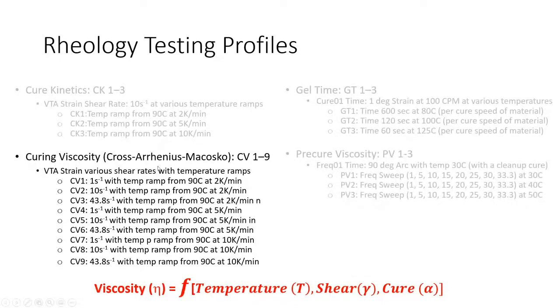Thank you. In curing viscosity, we use a little higher one. I think we use 3 degrees. We have to go to 3 degrees to push the motor limit. Everyone asks me, why do you go 1, 10, and why didn't you go 100? Well, that's why I covered the motor limit. 43.8 is maxed out. That's the most I can do.